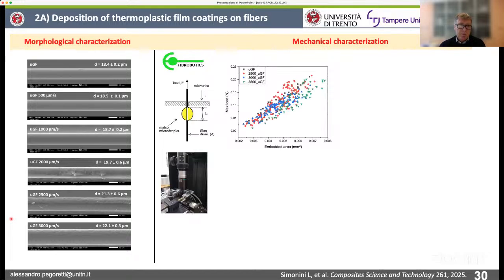At this point, by using the machine I already introduced before, in collaboration with Fiber Robotics, we basically measure the adhesion with a large number of experiments. If you do these experiments manually, it takes too much time. It is not possible. So you really need an automatic machine to do this type of test, in which we can deposit several droplets, more than 30, 40 on the same fibers, and then test them in a quite automatic and continuous way.